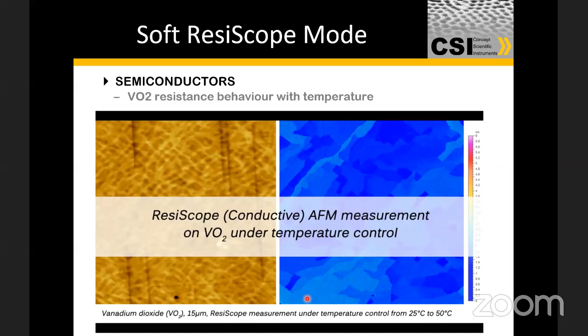And you can do this obviously in temperature control as well. This is one illustration where we can actually look at the change in behavior of this particular vanadium oxide as you change the temperature. So its resistance behavior actually changes with temperature, and we're able to capture that using the Resiscope and constantly ramping up the temperature of the sample. In this case, only a slight change between 25 to 50. So you can see that the whole resistance pattern on the surface itself changes.